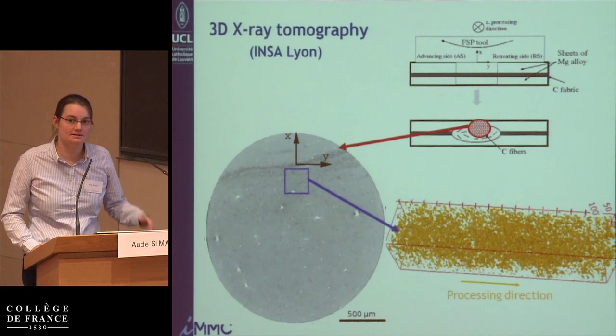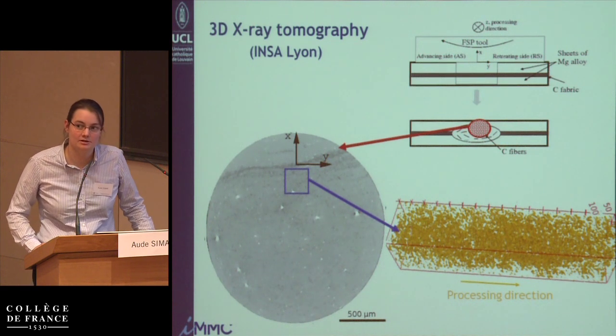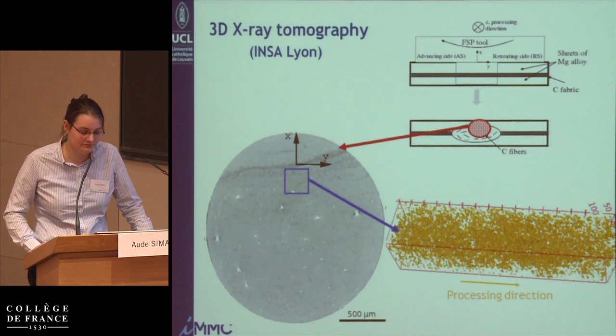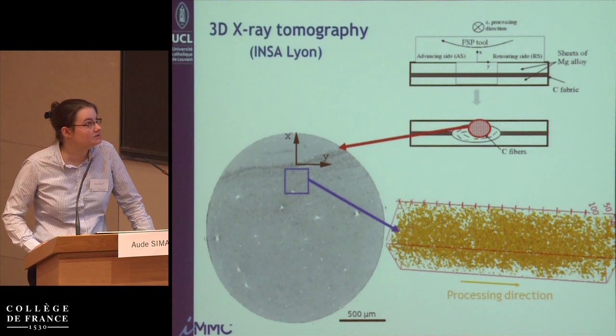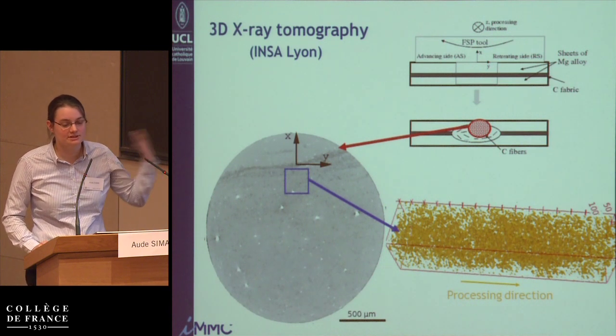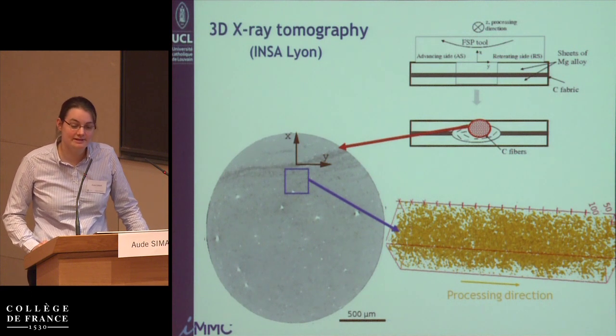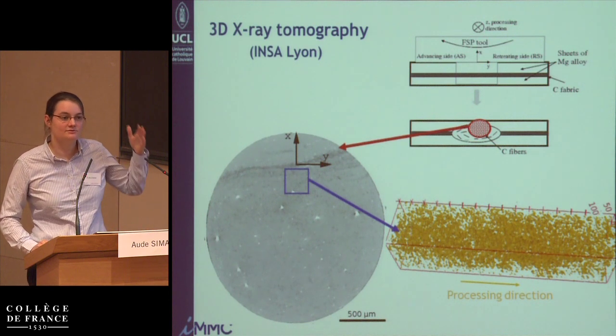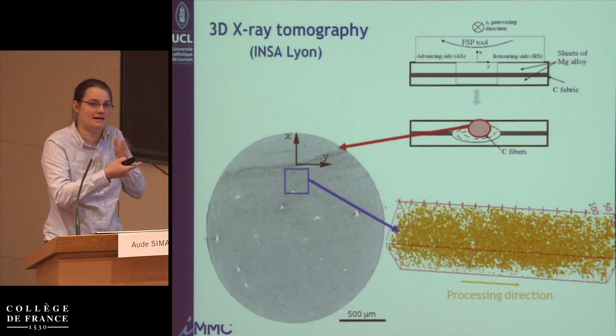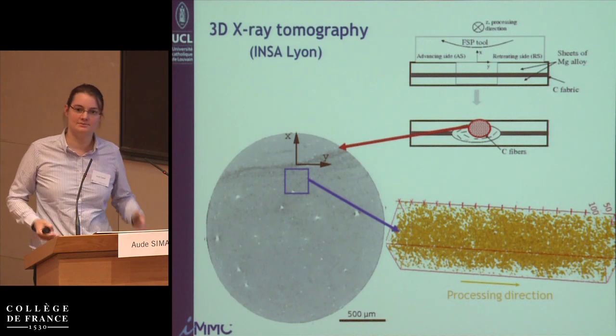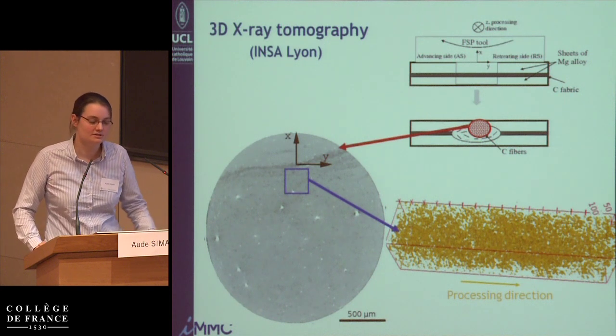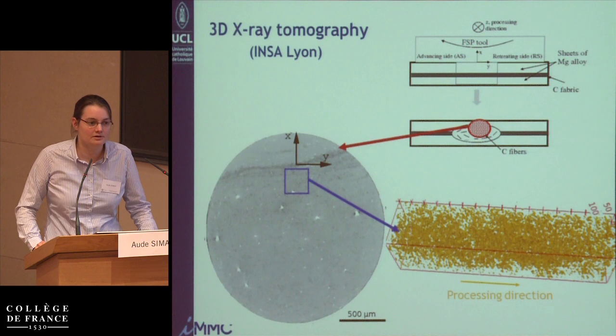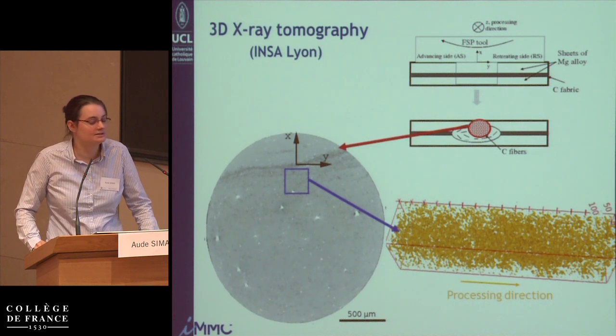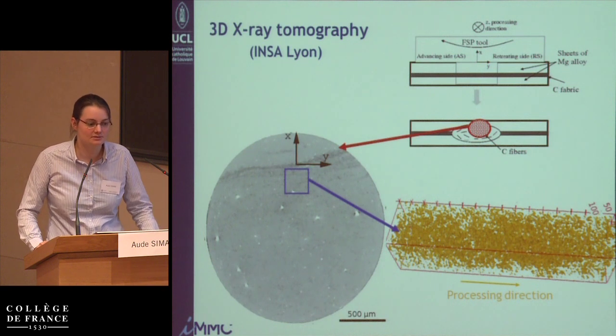To look a little bit at the 3D shape of this distribution of these carbon fibers, we looked in 3D X-ray tomography. All the images that I showed you before were 2D images, and 2D images that you get from scanning electron microscopy, but that gives you a cross-section of a fiber that can have different orientations. So it's nice for estimating surface fraction that you can eventually extend to volume fractions, but it's also nice to be able to see how they distribute in 3D.